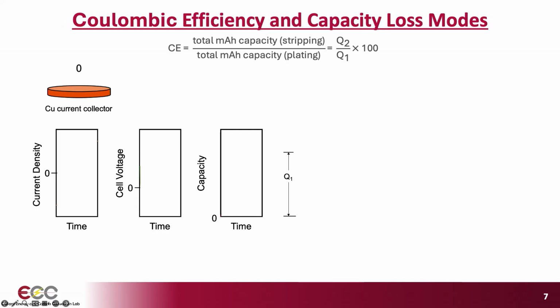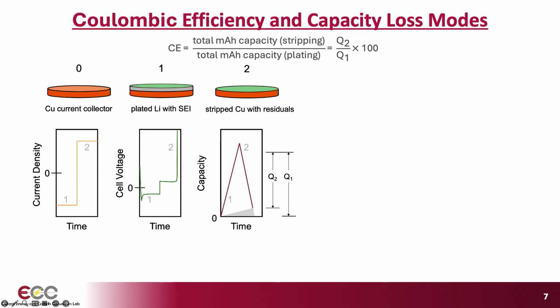So the key performance metric for measuring or determining the reversibility of lithium plating and stripping is the Coulombic efficiency. And we measure it as is shown here. So we have a copper current collector, that's our working electrode. And there's an opposing lithium reservoir that's not shown here. And we apply a reducing potential. We plate a certain amount of capacity onto the current collector, Q1. Some of that will plate as metallic lithium. A degree of that will react to form the SEI. And then we reverse that process, do an oxidation reaction, and strip as much of the reversible lithium back, and that gives us some charge Q2. And so the Coulombic efficiency is determined, at least in the simplest case, as the ratio of Q2 to Q1. There are other ways that we measure it, but this is the most straightforward.